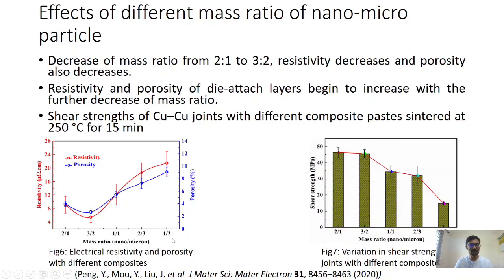As you can see, these are the 5 mass ratios that we have taken, like 2:1. Here the ratio is between nanoparticles to microparticles. So 2:1, 3:2, 1:1, 2:3, and 1:2. As you can see, when we have decreased our mass ratio from 2:1 to 3:2, our porosity and resistivity both get decreased, and we get both good thermal conductivity and good electrical conductivity at this ratio. But when we decrease this ratio to 1:1, our resistivity and porosity get increased again. So it is better to keep the ratio at 3:2.